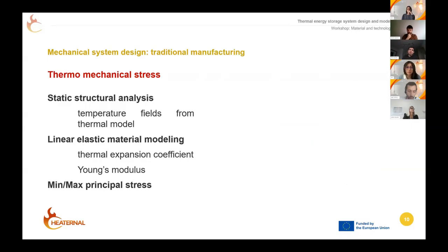We do a static structural analysis. So we take our temperature fields from the thermal model, implement them in a mechanical one. We use linear elastic material modeling, basically because of the simplicity, and it is a conservative approach to material strength, and we want to be conservative in this regard. And we apply a minimal maximal principal stress criterion to check if our design is good.